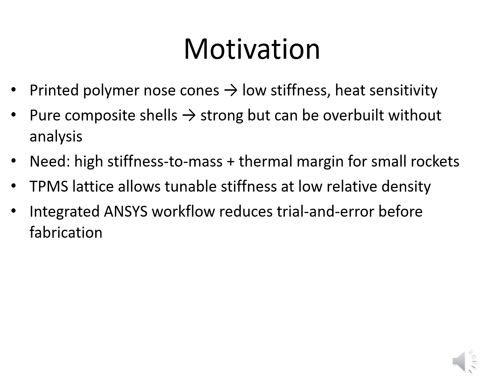Our approach aims to combine the best of both worlds by using a very thin composite skin to provide high stiffness and strength, supported by a TPMS core that stabilizes the skins and prevents buckling. This sandwich approach significantly increases the stiffness to mass ratio while keeping manufacturing accessible. To evaluate this design, we use a fully integrated ANSYS workflow linking CFD-derived pressure loads, Material Designer homogenization for TPMS, composite ply analysis, and thermal simulation. This reduces the guesswork and allows us to refine the structure before any physical prototyping.